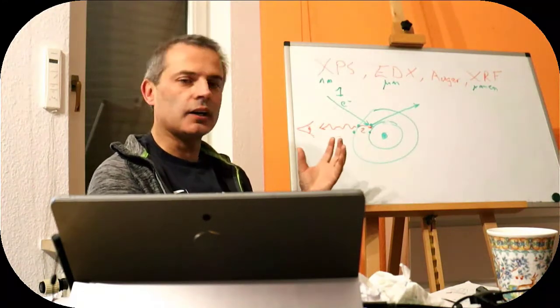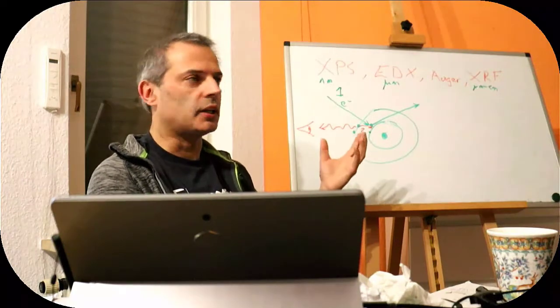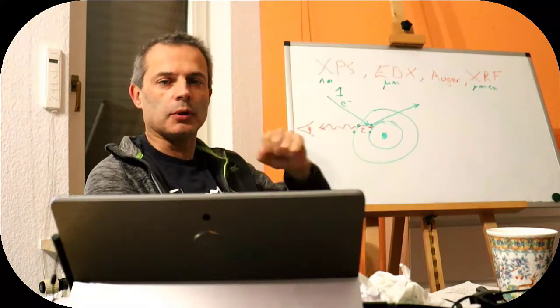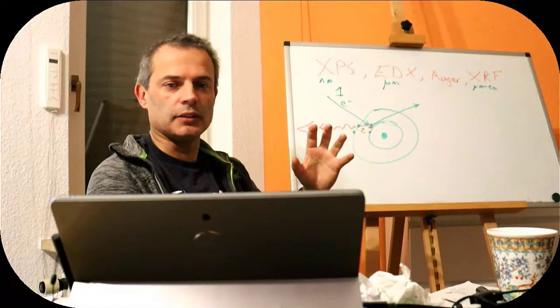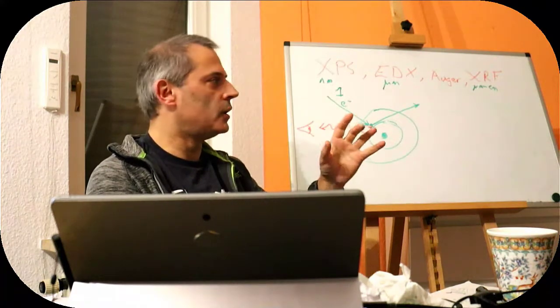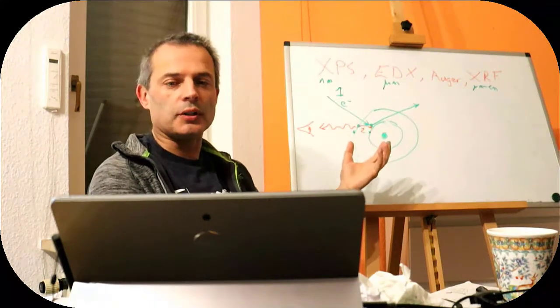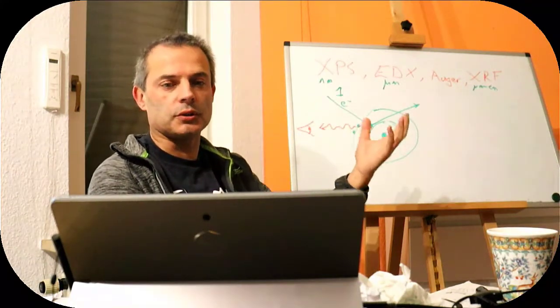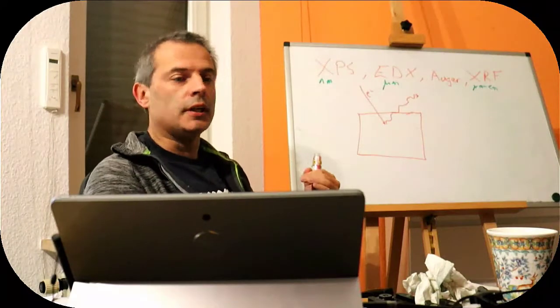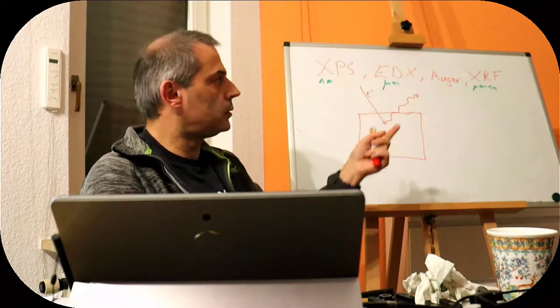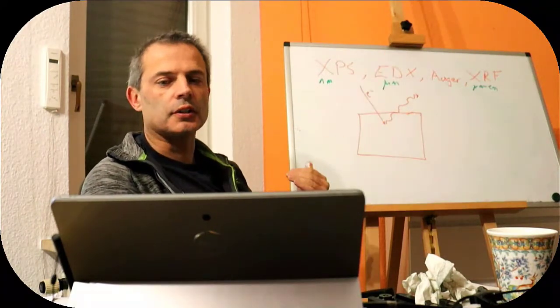So if we're unlucky, we can end up with a particular constellation that looks like it might be calcium carbonate, but they're not actually connected to each other. And reminding you that we can't see hydrogen means that whether it's got an OH on it or not is completely impossible to tell. The reason that EDX is comparatively deep, it goes down micrometers into the surface, is that